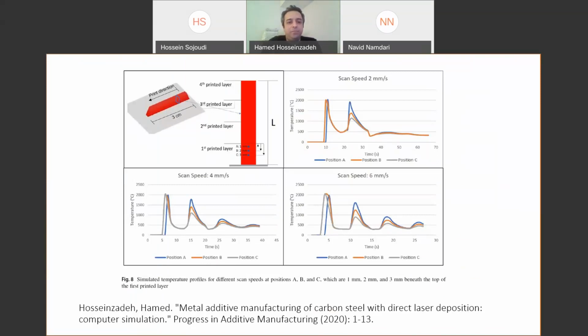For example, in this figure, we have 4 layers printed on each other with the DLD method, and we have 3 sensors, A, B, and C. You can see the distance of each point from the top of the first printed layer. And if you check the graph, you can see we have different scan speeds, 2, 4, and 6 millimeters per second, and you can see the difference between each layer. I don't want to discuss the effect of scan speed, I just want to show you the capability of the simulation.